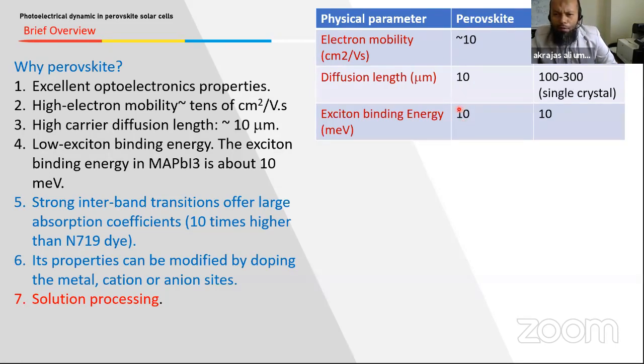The most important phenomenon that may be beneficial for solar cell application is that perovskite has low exciton binding energy, around 10 millielectron-volts, which is similar to silicon. Actually, this value is only 1/3 of the thermal energy at room temperature. So it means that during the photovoltaic process, we can easily dissociate electron and hole to produce photocurrent. Another interesting feature is that perovskite has strong interband transition that offers a large absorption coefficient. This means that perovskite can absorb a large density of photons to produce a large density of excitons. Then we expect a lot of photocurrent can be produced from devices using perovskite.